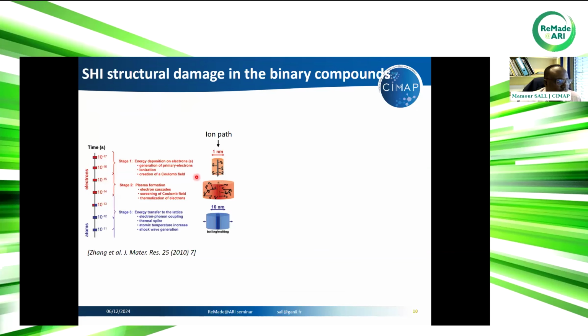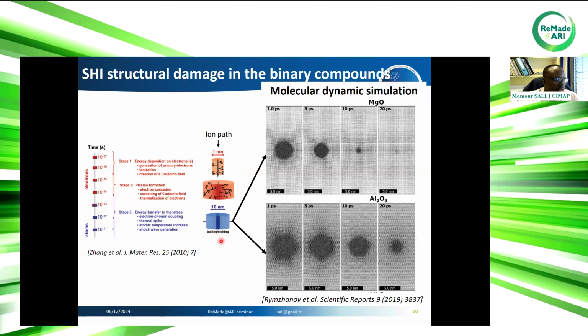So once again, how do we create defects with electron excitation? The ion transfers its energy to the electrons. The delta electrons create an electron cascade, and then the energy of the electrons is transferred to the lattice. So then we melt the material locally. This melted region will be, let's say, the initial point of track creation in the lattice. From this, colleagues from Russia, Rymzhanov and co-workers, have used molecular dynamics simulation in order to follow the evolution of the melted region as a function of time in two different materials. They did it in MgO, magnesium oxide, and also in aluminum oxide, sapphire.